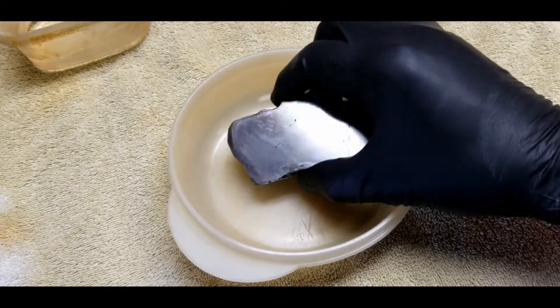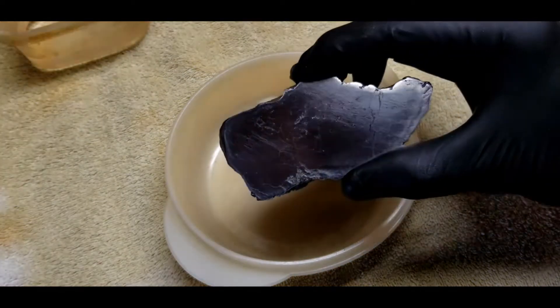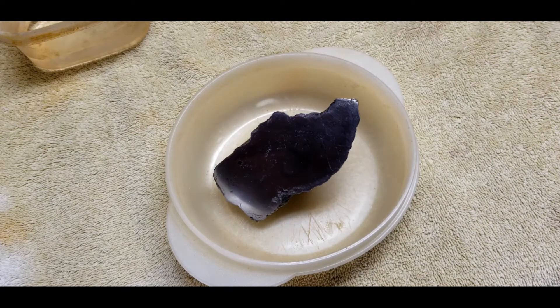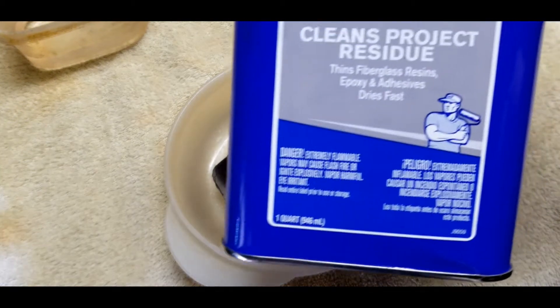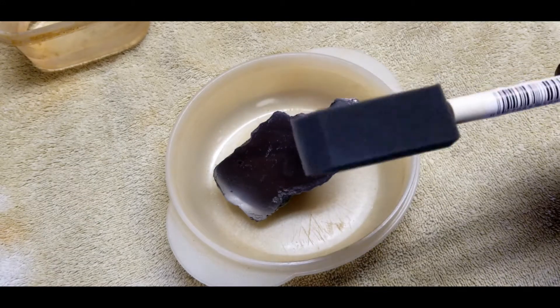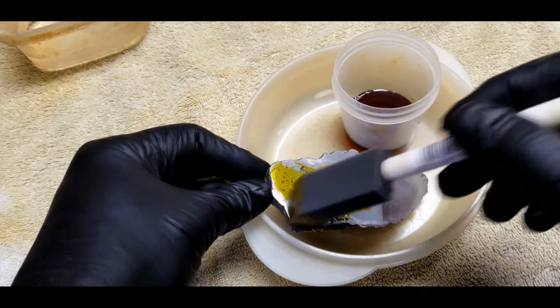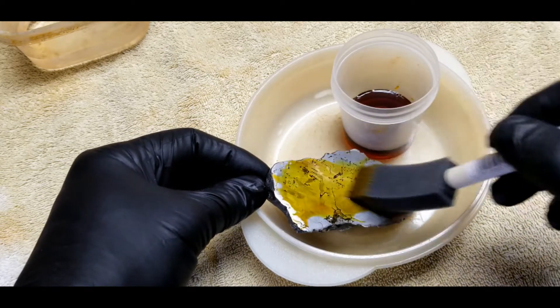Today I'm going to etch this piece of Odessa. It's a piece I've had for quite a while — it needs to be re-etched, it was a little rusty. I polished this down to 800 grit; I'm experimenting today because this wasn't a very expensive piece. I've got all my usual ferric chloride, and I'm going to neutralize that with baking soda this time. The surface has been cleaned with acetone, all nice and spot free. I've got distilled water and a little foam paint brush. I went to foam brushes because they apply the acid much more evenly in a controlled manner.